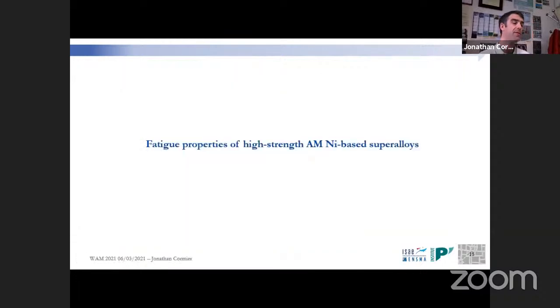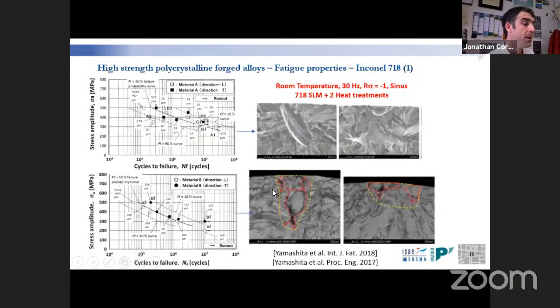Okay, so after those monotonic properties, I want to move to something really important when we need to consider certification rules of components for aero engines, so the fatigue properties especially. According to the literature, focusing on AM material, I'm still considering the case of 718, which is a weldable alloy. I just want to summarize rapidly that most of the issues are coming from processing defects.